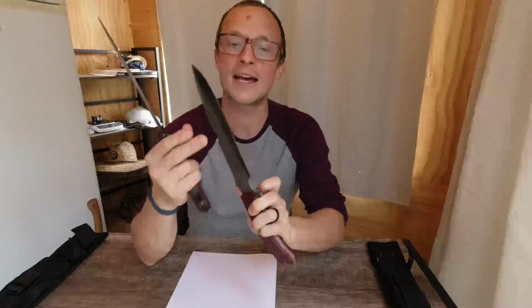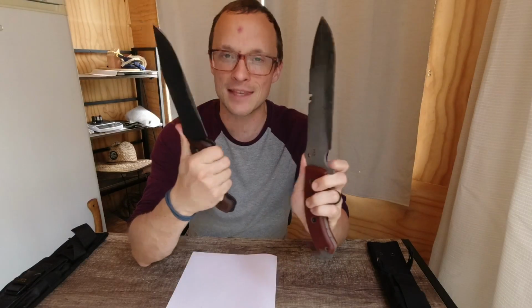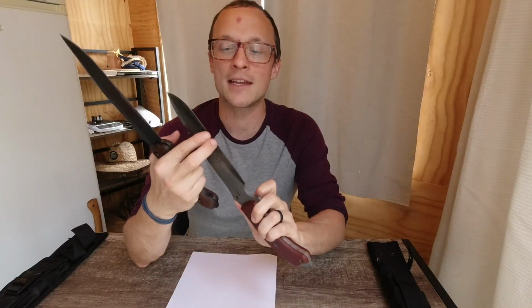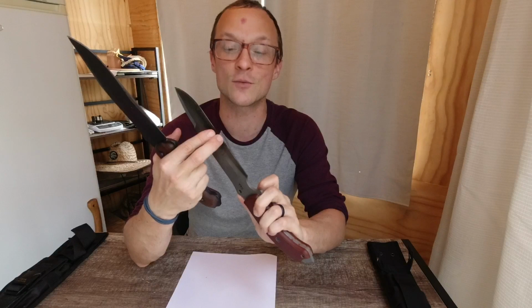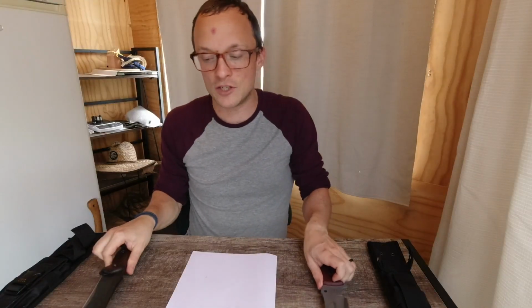I assume the Tops, with their differential heat treat, has reached a higher hardness than the KaBar Becker, and that higher hardness has resulted in less damage to the edge in the spot that does the bulk of the work. But perhaps the slightly higher hardness doesn't cope as well with hitting hard stuff in the dirt.